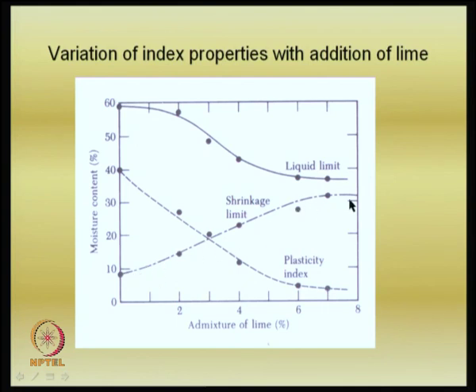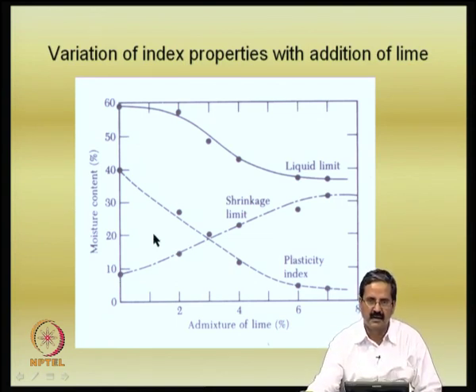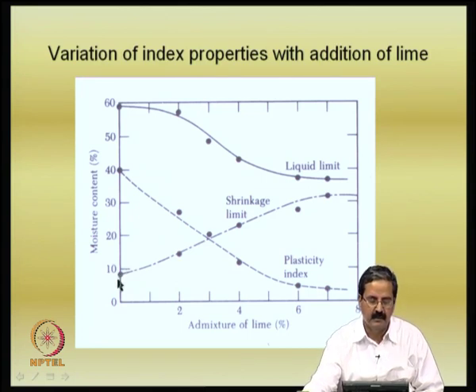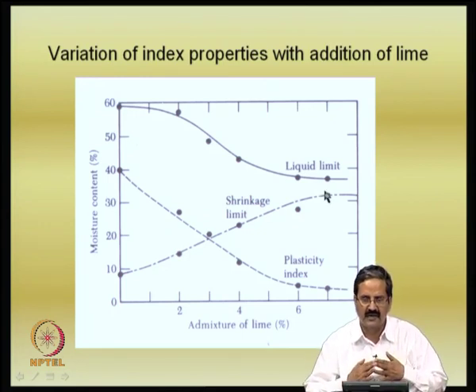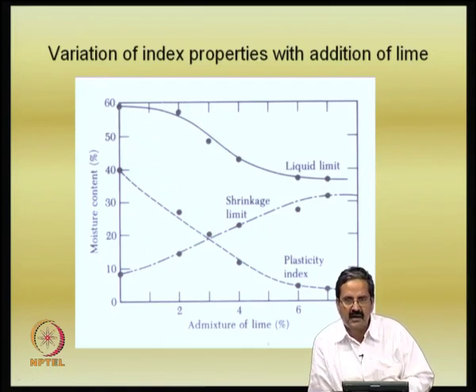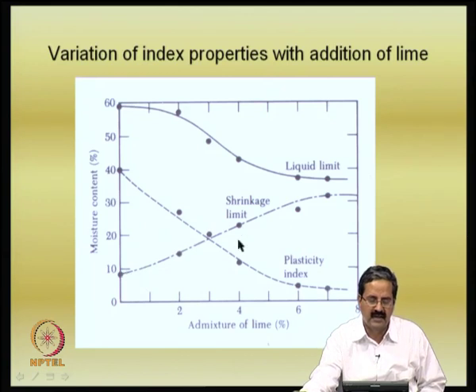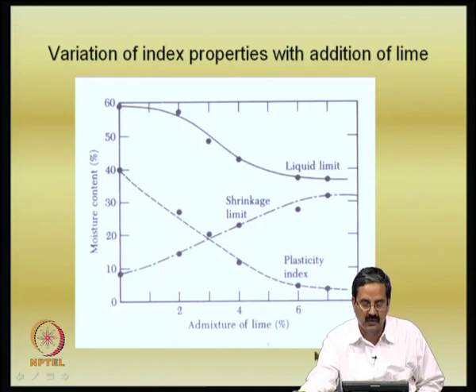As mentioned earlier, particles in a parallel plate arrangement like bentonite will have very high water content and very low shrinkage limit. The moment you add lime, the particle arrangement changes and it holds water differently. The edge-to-face flocculation occurs, and as a result the shrinkage limit is a little higher and the plasticity index is also lower, meaning you have comfortably reduced the plasticity characteristics of the soil and made the soil not so much shrinkable compared to before.